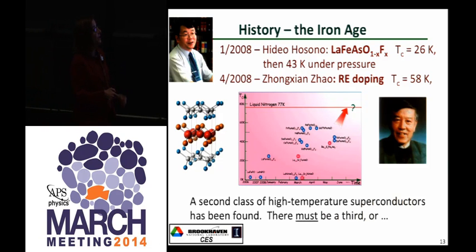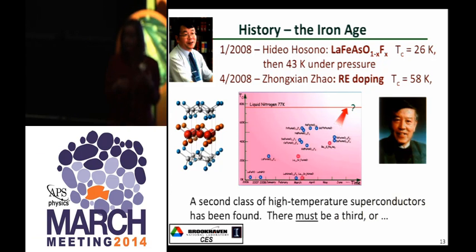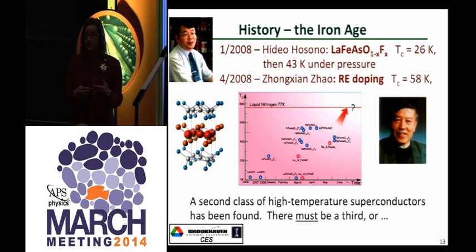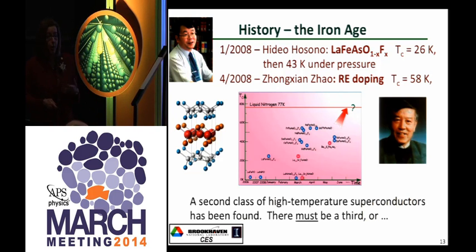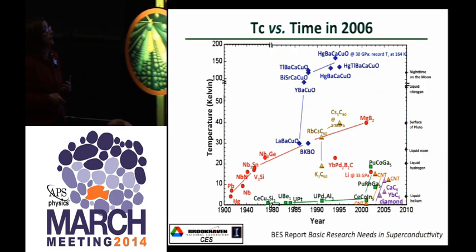The Chinese group, Zhao, pushed this up to about 58 degrees very quickly by substitutions, and it was a very exciting time. And there's a huge amount of data on here. And I think not only did it make us look for new superconductors, if there's two classes, there must be a third, the cuprates and the iron-based, but the comparing and contrasting of these two very different kinds of superconductors is helping us understand what might be the mechanism and what's going on here.